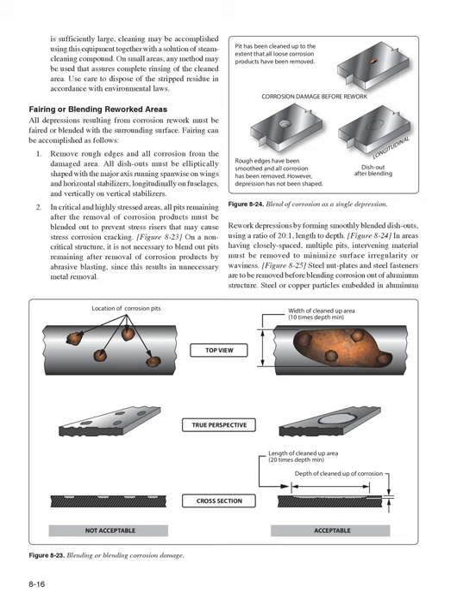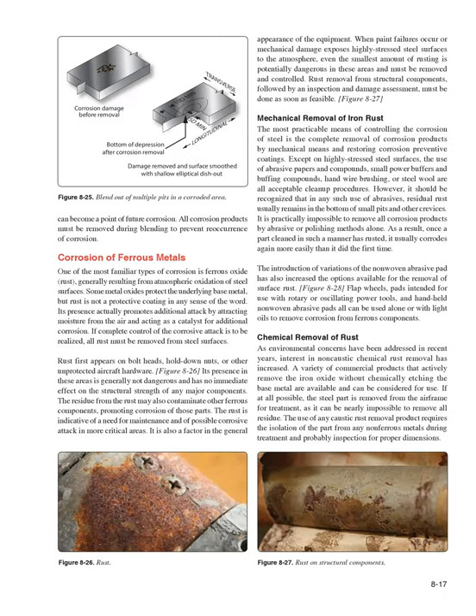Figure 8-24. In areas having closely spaced, multiple pits, intervening material must be removed to minimize surface irregularity or waviness. Figure 8-25. Steel nut plates and steel fasteners are to be removed before blending corrosion out of aluminum structure. Steel or copper particles embedded in aluminum can become a point of future corrosion. All corrosion products must be removed during blending to prevent reoccurrence of corrosion.